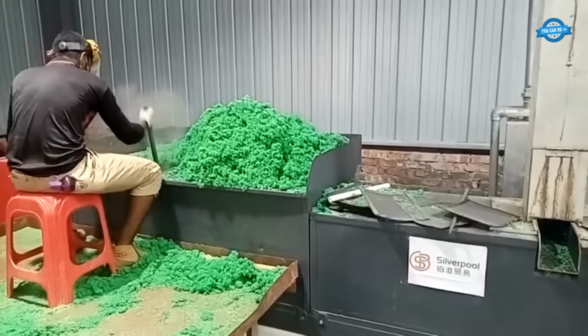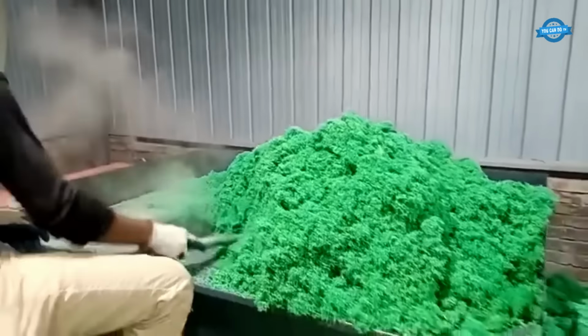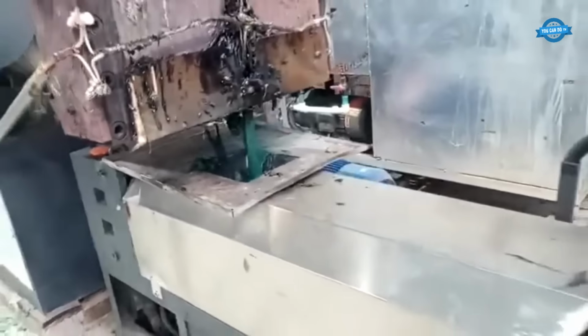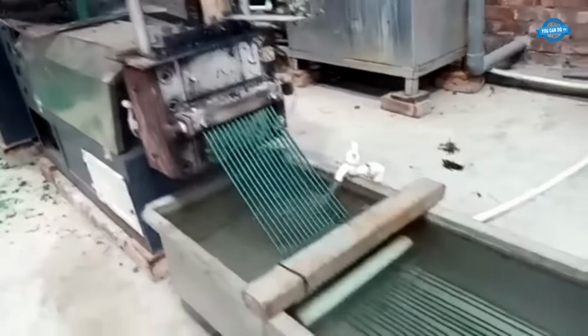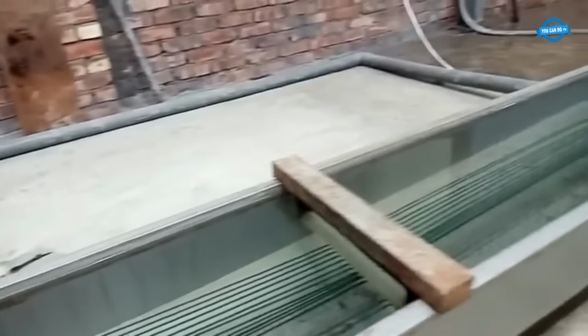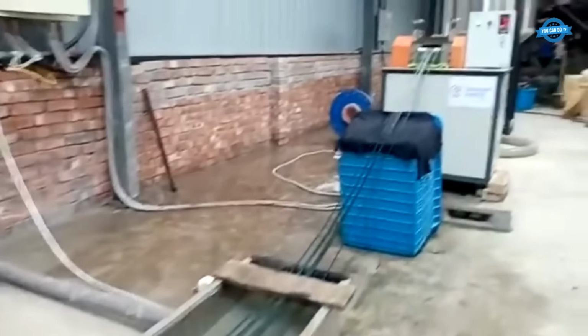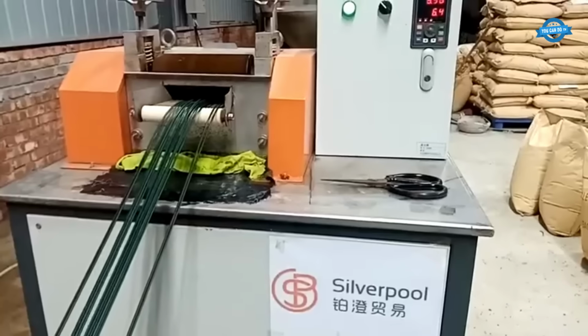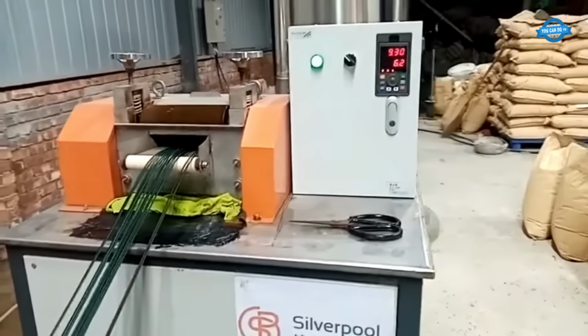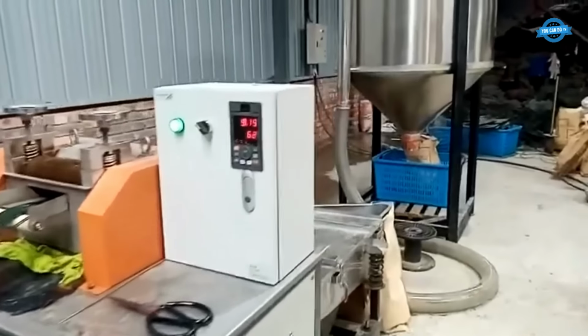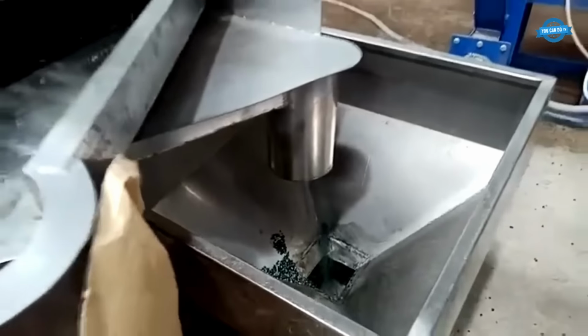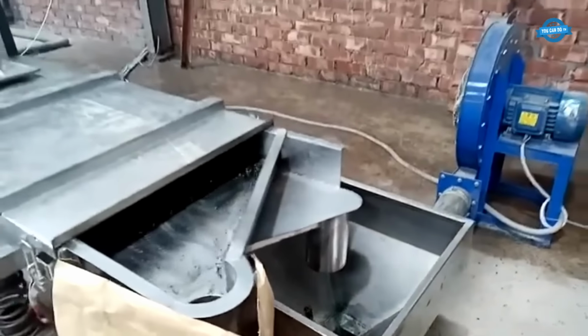Discarded fishing nets, or ghost nets, recovered from the ocean often contain nylon polymers that retain material value after cleaning. The nets are shredded, melted, cooled into strands, dried and pelletized into uniform recycled granules that can re-enter industrial production rather than continuing to trap wildlife on the seafloor. Successful pellet output depends heavily on contamination control. Excess salt, sand, or mixed polymers can destabilize extrusion and degrade pellet quality throughout the run.